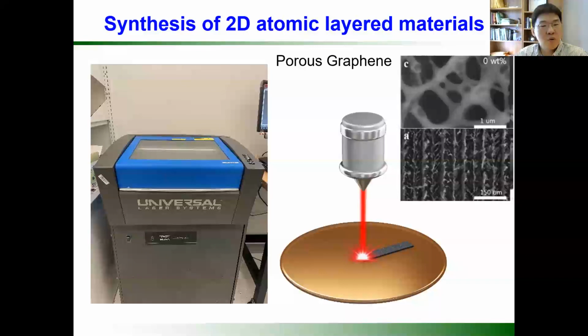And we can also fabricate the device. Usually graphene requires us to transfer it to a different substrate to make the devices. But using these laser techniques, we can synthesize materials very quickly, and at the same time we can fabricate the device using these printing methods. So this laser allows us to synthesize the material and simultaneously fabricate the device. So this is how it looks.